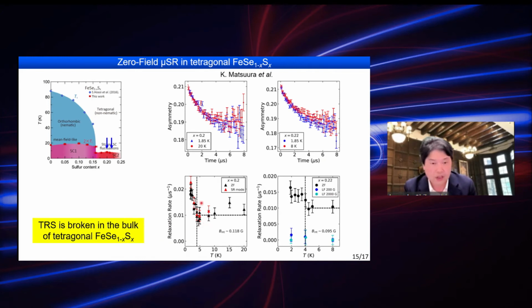So from these data, we conclude that time reversal symmetry is broken inside the superconducting state, both within the nematic phase and outside the nematic phase.